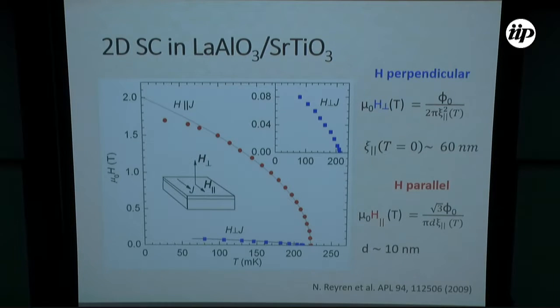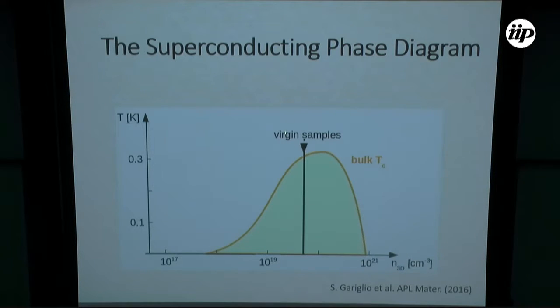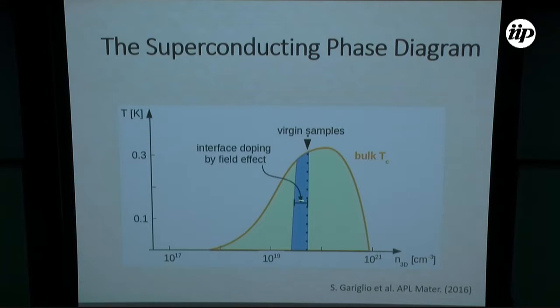So with the two-dimensional carrier density and the thickness of the superconducting layer, we can put our virgin samples in the phase diagram of the bulk. And we see that we are here. And now we know that by field effect, we can deplete or accumulate a little bit of carriers around this region with respect to the 3D carrier density, but we don't span all the phase diagram. So why do we have a suppression of TC on both sides? So that's a question I will try to answer with the measurement in field. So what we did was to take another sample, where here you see the channel, the backgate, and the voltage contacts.